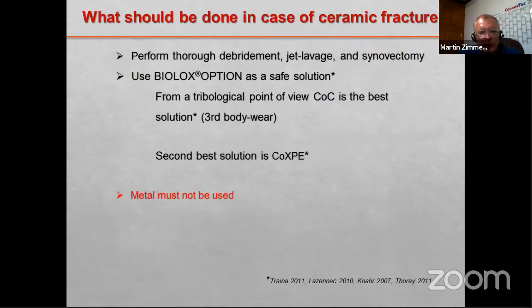That means if you use a combination of a metallic ball head against polyethylene afterward, with the presence of these ceramic particles, you're creating a grinding machine and a real problem. I will show you a lot of publications about that. So the metal head must absolutely not be used as a replacement after a ceramic fracture.